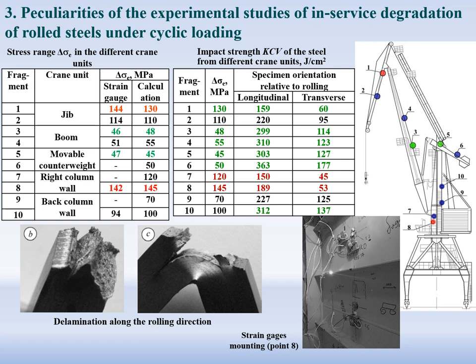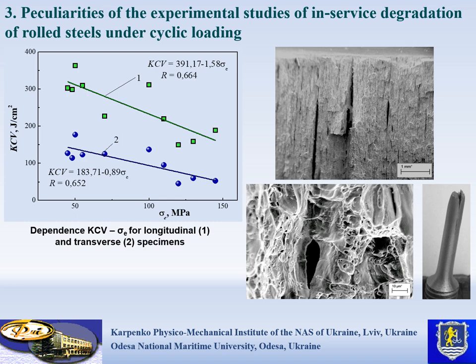The philosophy of such an approach is shown on the bright example of a sea portal crane, which served about 40 years in the conditions of long-term cyclic loading. A level of degradation of the rolled plate steel was dependent on a level of operational stresses. On this slide, you can see the dependence of impact strength separately of longitudinal and transverse specimens on the calculated level of operational stresses. The higher the level of stresses, the lower the level of impact strength.